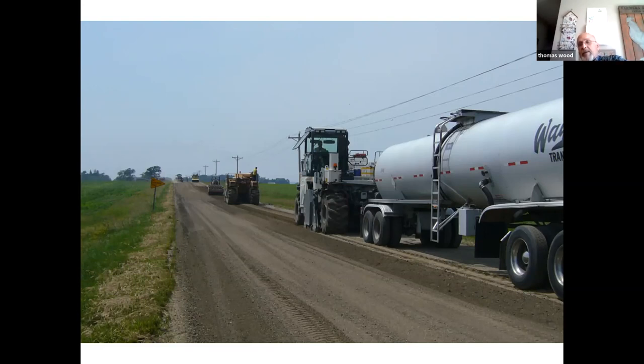But they're doing a second mix there, because what can happen, depending on the reclaimer, when you inject the emulsion in, if you only use the front reclaimer, you can end up with a bottom layer that is a little heavier on emulsion because it settles in the bottom of the teeth. So what this contractor was doing was injecting for 6 inches, or stabilizing 6 inches. So he set this front machine up so when it was 5 inches deep, the machine thought it was going 6 inches deep. So it's putting all the emulsion in for 6 inches.